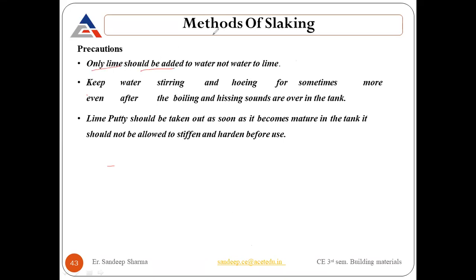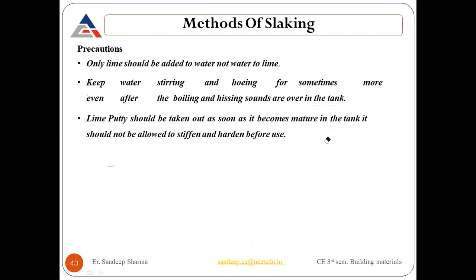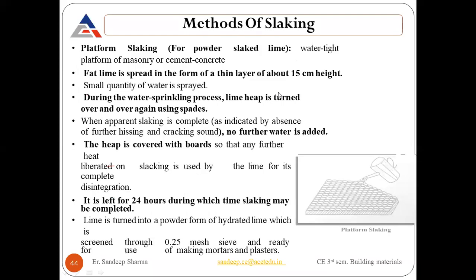Precautions during slaking: only lime should be added to water, not water to lime. Keep stirring the water even after the boiling and hissing sounds are over in the tank. The lime putty should be taken out as soon as it becomes mature in the tank and should not be allowed to stiffen and harden before use — similar to cement, which must be used before its final setting time.